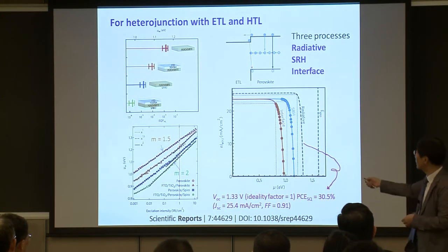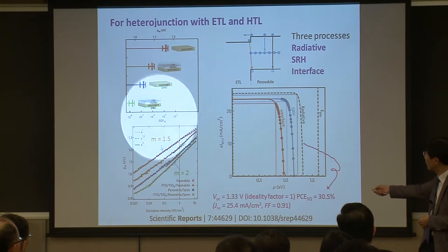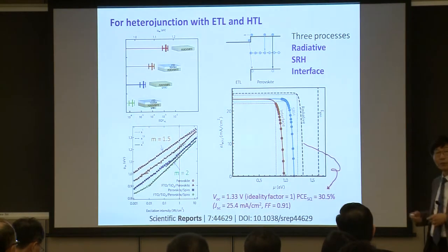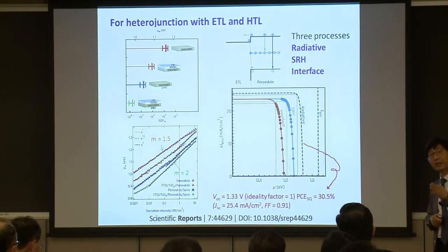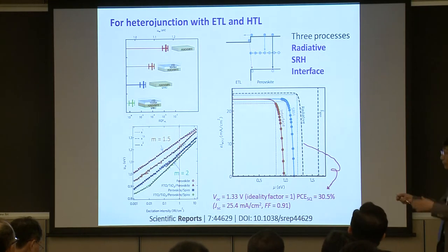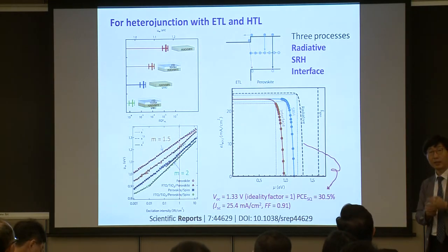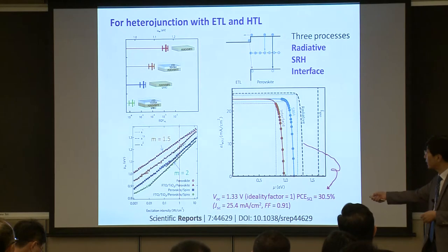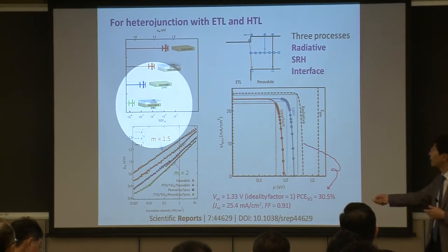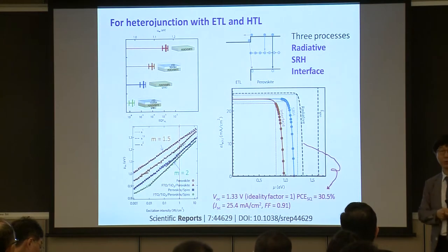Perovskite itself, for instance in PL, the external quantum yield is pretty high, but once you contact with the hole transporting layer or electron transporting layer, the PL quantum yield gradually decreases. And for both cases, the ETL and HTL, the further you decrease the quantum yield, the more you also decrease the open circuit voltage.